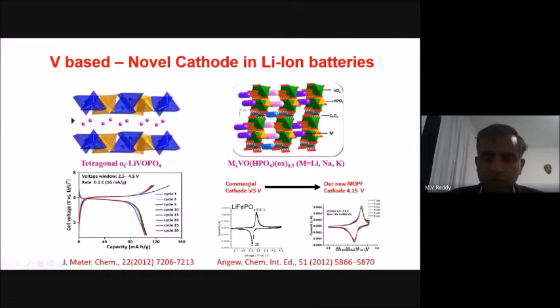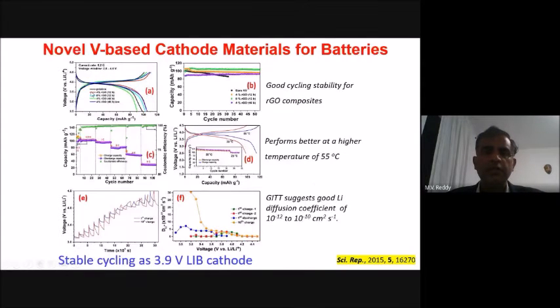Some early reports, reported for the first time in the literature, are on something like new metal organic inorganic framework materials. Compared to the benchmark material iron phosphate at 3.5, this is nearly 4.1, which means that we can still get high energy density. There is still a need for further improvement in the capacity. Although the voltage is really good for practical applications, the capacity has to get higher, and only then can we use it for practical applications.